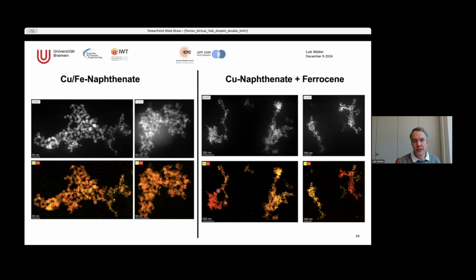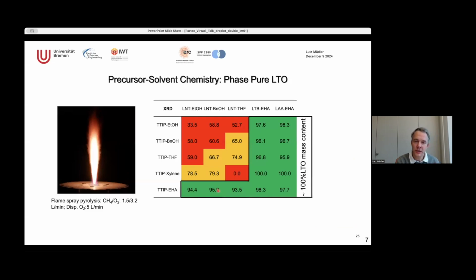So to make my story, if you really want to have this lithium titanate and you want to have it phase pure, you need to make sure things come out at the same time. And you need to make sure you understand this precursor chemistry and this whole explosion event. And if these happen, we now know that you actually can get very phase pure and well mixed, atomically mixed multi-component metal oxides.